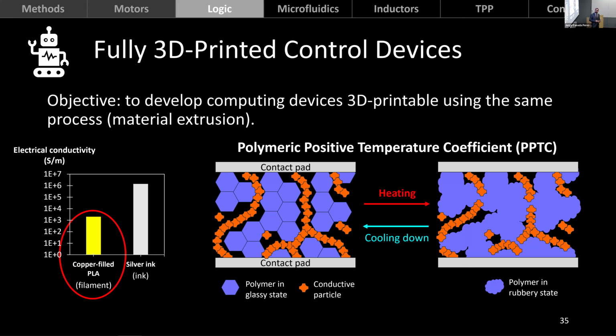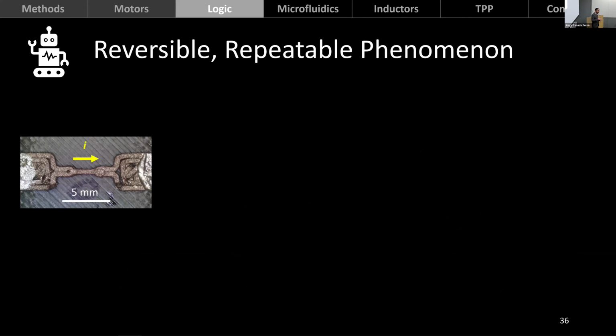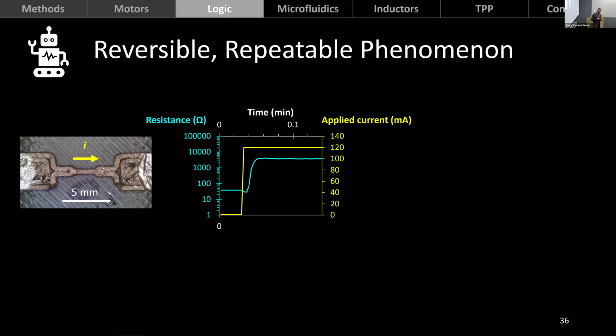And so we were able to find that this material exhibits that behavior. We were able to characterize it. This is the type of sample that we used for that. And we saw that if we apply a high enough current, in this case 120 milliamps, a little bit after applying that current, the resistance of this trace spikes by 2 orders of magnitude, which is very significant.